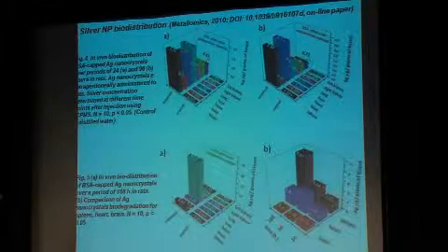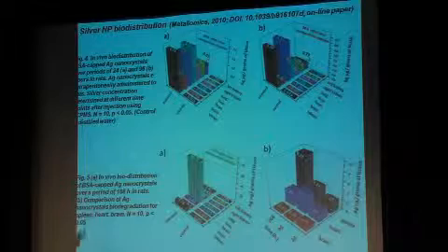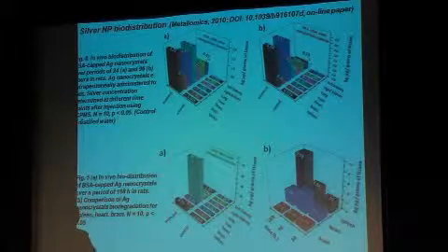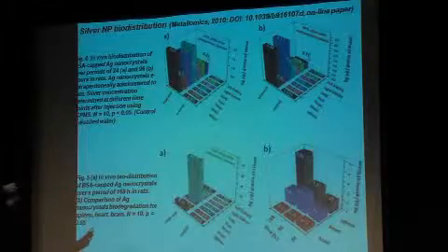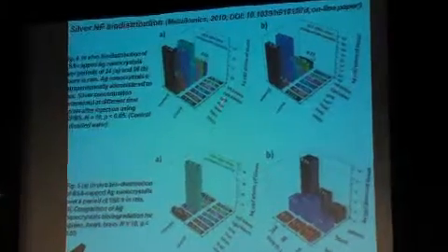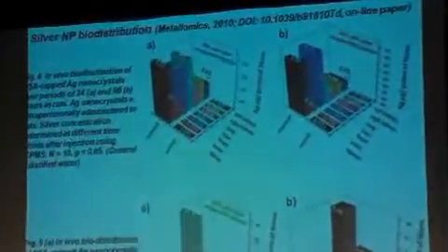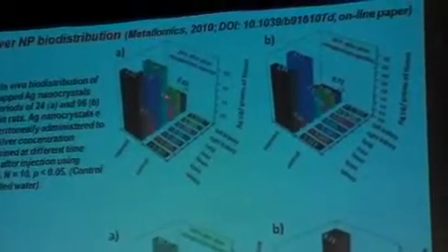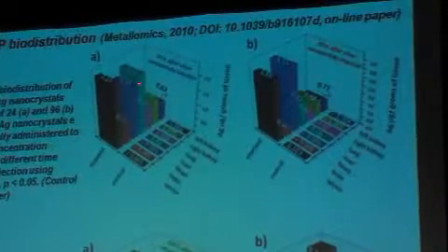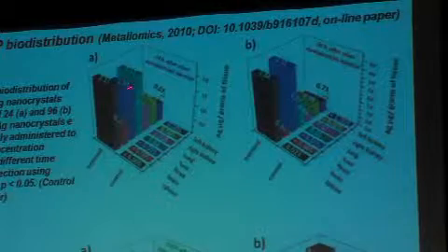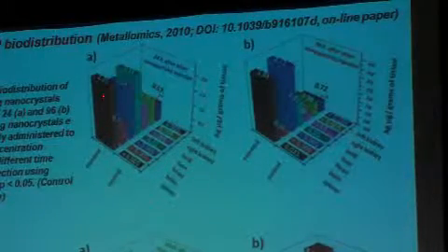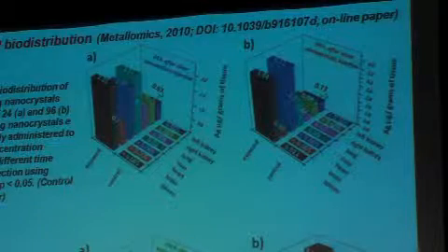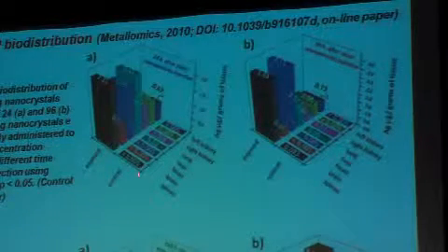So they have taken these silver nanoparticles and capped them with serum protein to make them serum compatible. They pre-cap them with serum protein, and they inject them into mice, and what we see is not surprising. The liver, the lung, the heart, the brain, the spleen, and you see that these particles all reside. These are the dosages that reside in those tissues 24 hours after injection. Most of them reside in the liver, the spleen, and the heart. All right, and this is the case when you don't inject particles, so this is the control.